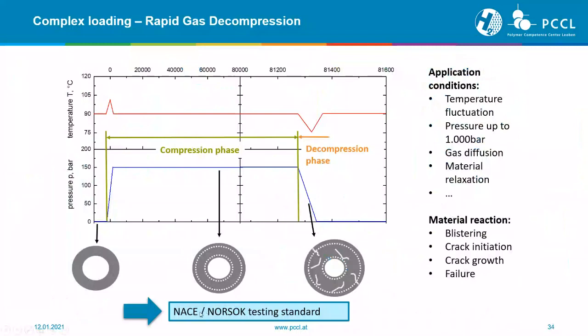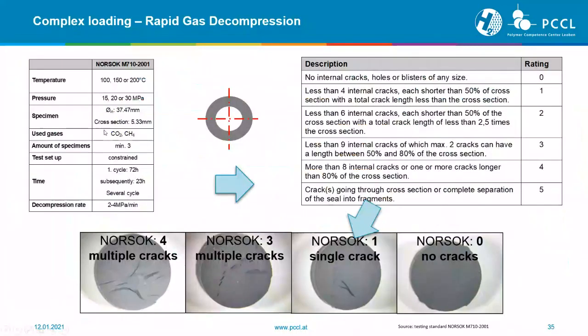Two testing standards are the NACE and NORSOK testing standards. They specify temperatures, pressures, specimen geometries, and also gases for the gas industry, in this case CO2 and CH4. Then you store your O-rings directly in the autoclave, test them according to the testing standard, and then you rate the cross-section of your O-rings after the tests, which means that you cut the O-rings you get out of the autoclave into 4 pieces. Then you use a microscope or a camera to make pictures of this cross-section, and you count what's happening, how many cracks you can measure and how long the cracks are. Then you have a rating from 0 to 5, where 0 means no cracks, so very good, and 5 means complete separation of the seal into fragments, which means completely failed.